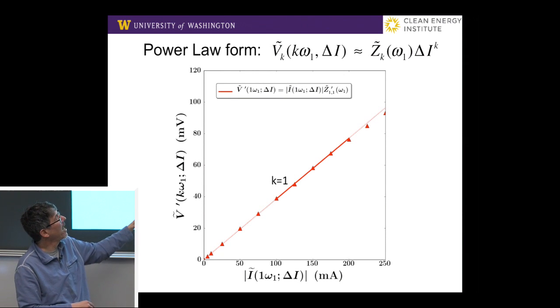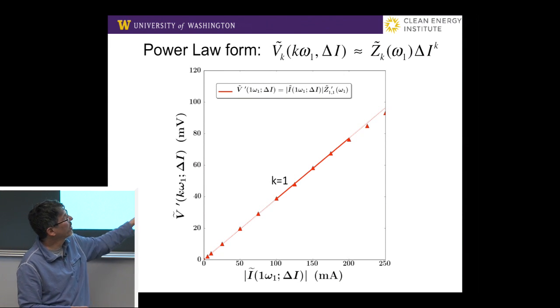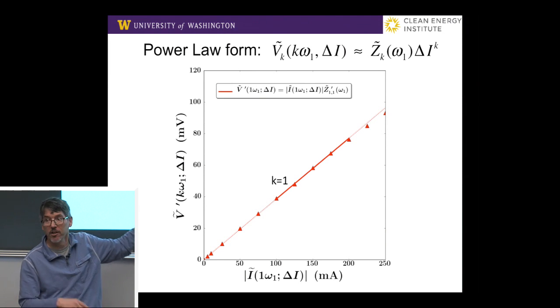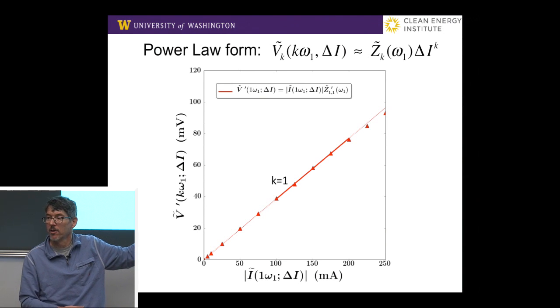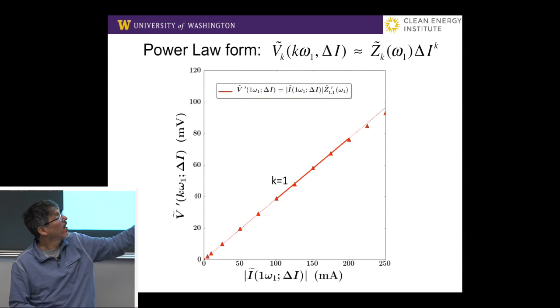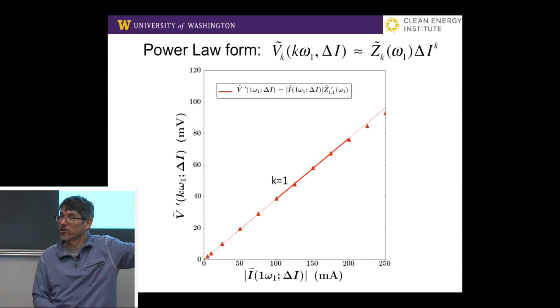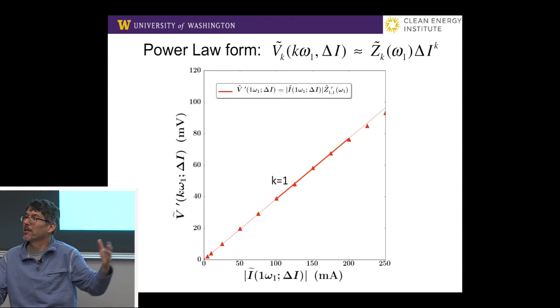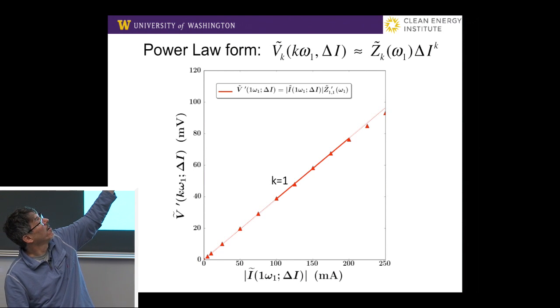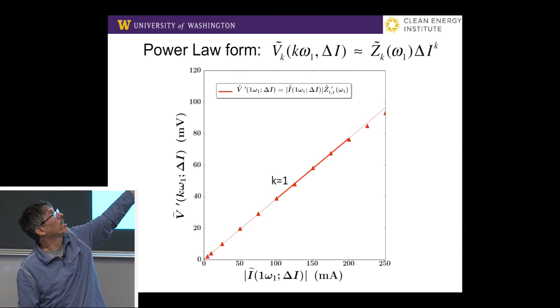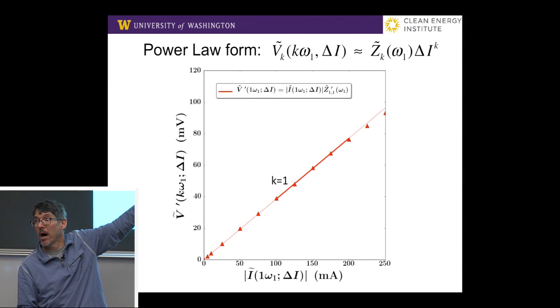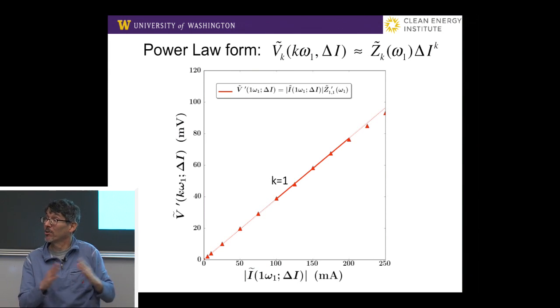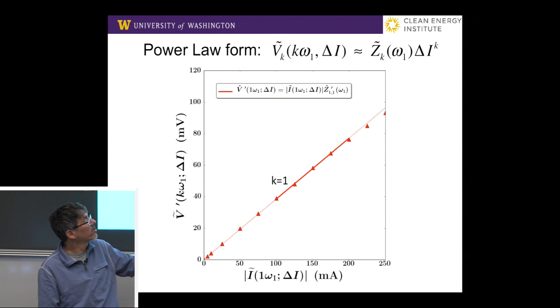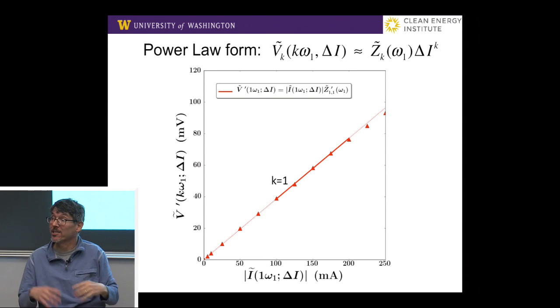But anyway, here's K equals 1. As we increase it, the voltage modulation of both the real and the imaginary components rise linearly until we get to the higher values and it starts trailing off. And we're going to just look at the leading order solution. That's why I say V is about equal to Z_k times delta I raised to the k power. So the k is 1 in this case, so it's linear. And we're going to use values to get the slope, which is going to be the impedance,